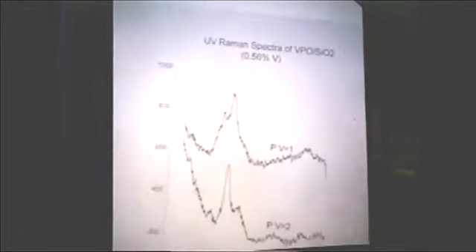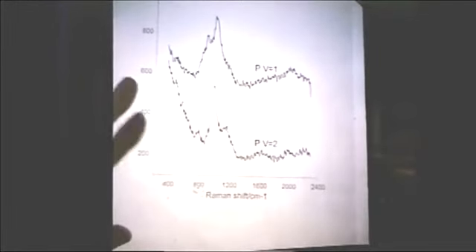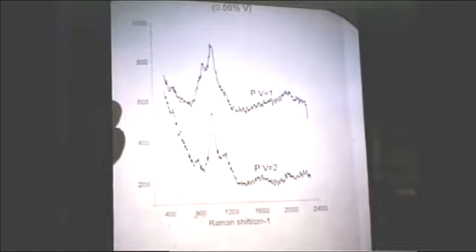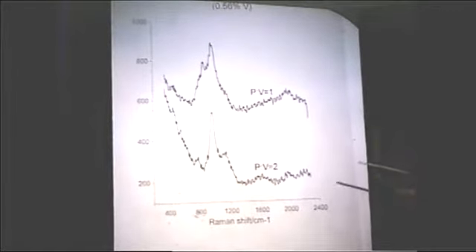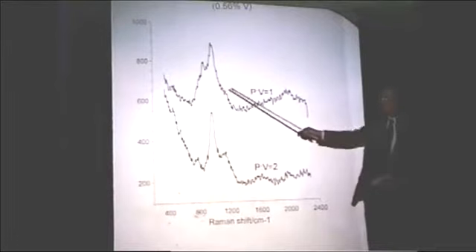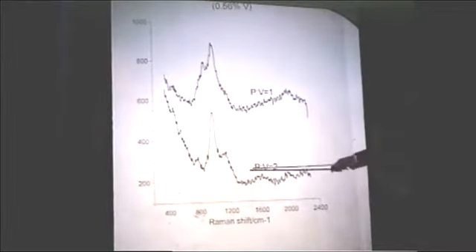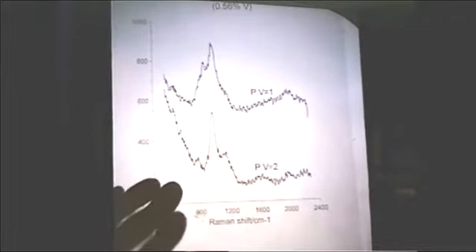We've also looked at a supported oxide catalyst. This is a catalyst that we got from Harold Pung's group. We wanted to compare the sensitivity of our instrument to one that he has in his laboratory. This is a very low weight loading of vanadium, VPO on silica. And Harold can't see anything in his spectrometer. But in our spectrometer, we can get a nice spectrum characteristic of the VPO species on the surface, and you can see it even changes as the phosphorus-vanadium ratio changes. So it seems like this is a very nice way of looking at catalysts.